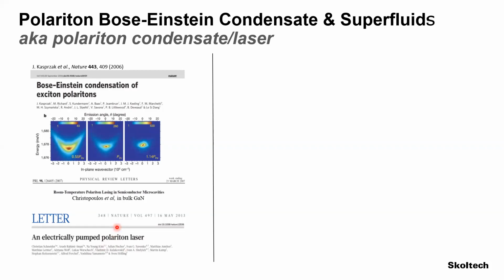What is the picture snapshot of the light? Yes, so the picture here that you see is what I was showing before, energy versus in-plane momentum. They have not plotted on top the dispersion, but the dispersion is this lower polariton dispersion. And you see the photoluminescence as you increase the excitation density. So here you are below threshold, and you can go above threshold. And once you hit threshold, you see the collapse of all the polaritons in the reciprocal space. They all come out from the normal incidence, yes? So they collapse across the polariton dispersion to the ground state.